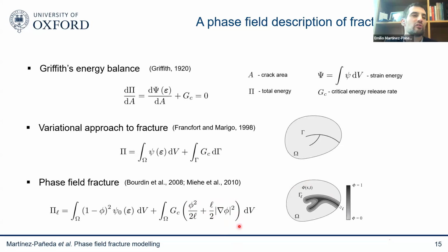But what this means from a computational perspective is that if your mesh is fine enough to resolve this length scale, your results are mesh independent. Your results are mesh objective. So that is one of the beauties of the method as well. But basically what the phase field allows is to regularize this functional. You go from a surface integral to a volume integral, and it's very easy to solve this problem now using the standard finite element methods.